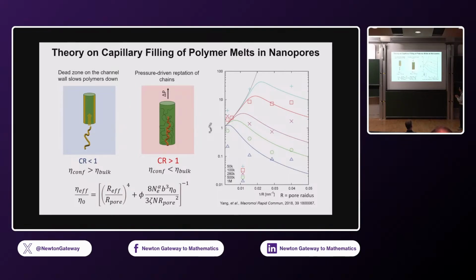But then there's this other effect where polymer is now reptating through this network of polymers, where the network of polymers also is driven by the capillary pressure. Okay? So there's convective movement of the polymer network that is moving, and there's reptation. So that they attribute to this region where you actually can see that the effective viscosity is smaller than that of the bulk viscosity. Okay, so the result that I just shared with you from our own lab, my own lab, seemed to agree with this picture quite well.